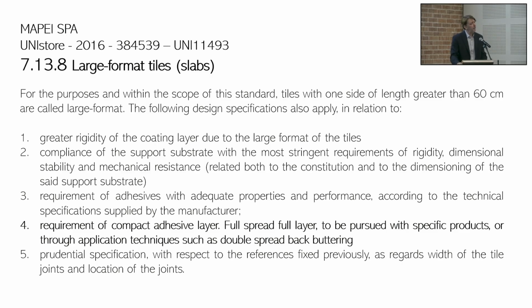Remember that if you have voids under the tile and water goes into the voids, because the water passes into the joint anyway, no matter what you do, it will pass into the joint, will go under the tile, and the water under the tile is a problem, because the water, time by time, will affect the adhesive and the adhesion.